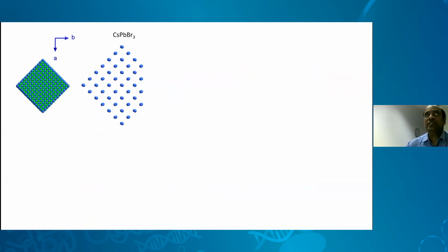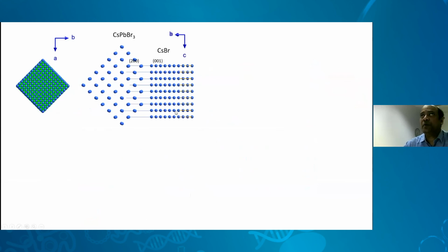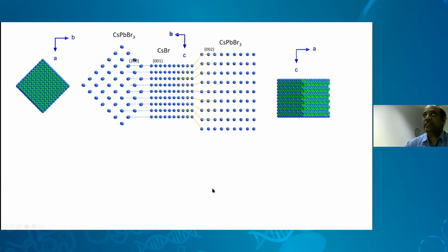So then what happens here, we put it out as cesium lead bromide. You see, this is only the cesium, but here is the cesium lead bromide. I picked up only the cesium template here. Then I put cesium bromide over here. So when you put cesium bromide first, then cesium bromide connects to these structures through lattice matching this way. Then when we put lead on it, that expands this way, pulling a different cube orientation.